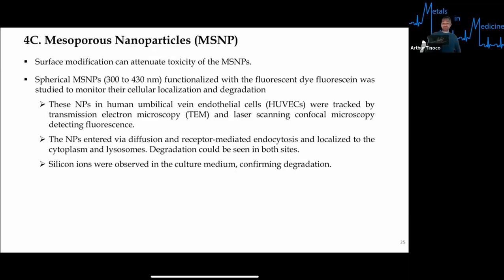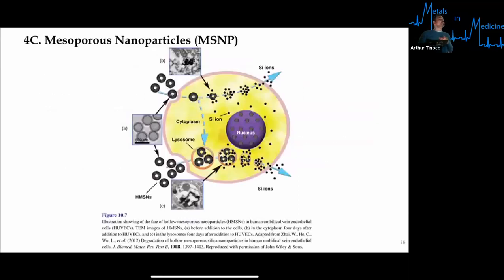The nanoparticles enter via diffusion and also by receptor-mediated endocytosis and localized to the cytoplasm and lysosomes. And in this process, degradation was observed via both routes of entry. So what are the degradation products? Well, they are the formation of silicon ions in the culture medium, and that basically confirms degradation. So here we have a visual of this process, where you have the entry through an endocytotic process or an entry through a passive diffusion, okay? And then the subsequent breakdown of the materials into these silicon ions. And so that gives you the perspective of how it can be used for delivery of something, but also that the material can be broken down.